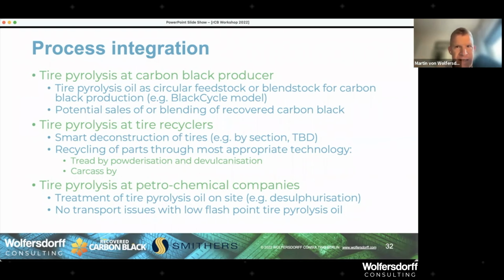Actually, the sulfur in the carbon black is really tied to the process type. I don't think that by residence time and temperature you can change a lot, but certainly the sulfur balance between the oil and the gas, you can work a lot by a fast or slow pyrolysis and a low temperature and high temperature pyrolysis. You can tell the sulfur where to go, and you want the sulfur in the gas because then you can just scrub it out, and the oil will be low sulfur. That is the value determining factor, the sulfur, in addition to density and the kinematic viscosity. So that could be process integrations.